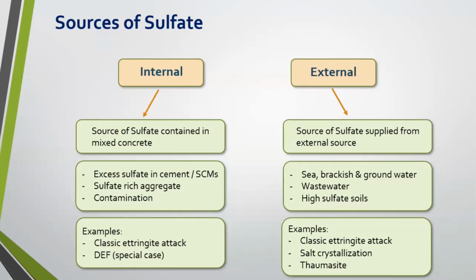Examples of this would be, again, the classic ettringite attack, salt crystallization. And the last of these examples I've got listed here is thaumasite. Now, I'm going to give this one kind of an asterisk because thaumasite occurs in some of the coldest places on the planet. And so it typically needs extended periods of cold weather is where you see this phenomenon happening. Thaumasite can be incredibly destructive because it actually attacks the CSH, or the calcium silicate hydrate, which is the glue that's holding our concrete matrix together.